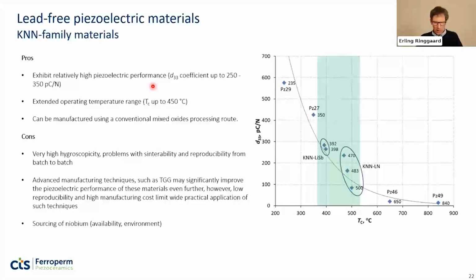Okay, so I think I'll make these examples short. I'll just mention for KNN that you generally get relatively high d33 coefficients and in some cases quite a nice operating temperature range. But there are certain problems with KNN that makes them difficult to make, and this is maybe one of the reasons that they are not really that dominant on the market as you could expect, since they have been under development for quite a long time. And one specific issue is also that it contains, of course, niobium, which is a more expensive material than the precursors for PZT, and there's also some environmental concerns with the niobium.